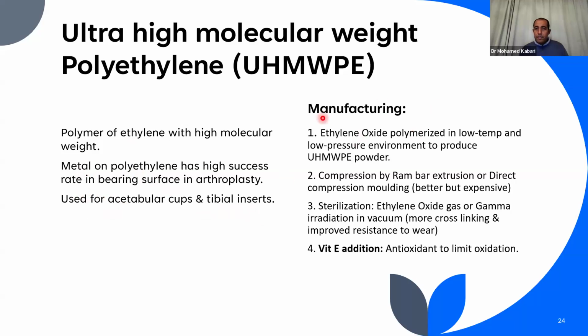The manufacturing of the polyethylene passes through multiple steps, starting with ethylene oxide polymerization in a low temperature and low pressure environment to produce the ultra high molecular weight polyethylene powder. Then compression by ram bar extrusion, which is like a machine putting the powder through to give rods of the polyethylene, or by direct compression molds. It has a specific mold to give specific shapes for the polyethylene, which is better but expensive.